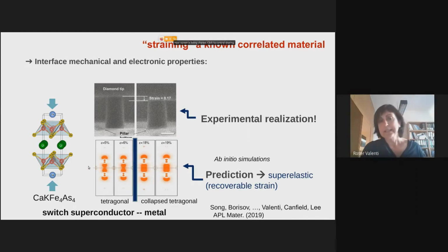So the prediction was that at a certain critical strain, you will have this bonding. You go from this tetragonal to this collapsed tetragonal state. But what is more important, you go from a superconductor to a metal phase, and this type of effect is reversible. And here is the experimental realization by Paul Canfield and Seok-Wook Lee, where they did, in fact, this experiment. You strain the system, it's a superconductor, you can strain up to 17%, and then the superconductivity is gone. But if you release the strain, it goes back to superconductor. So you can do this process back and forth.